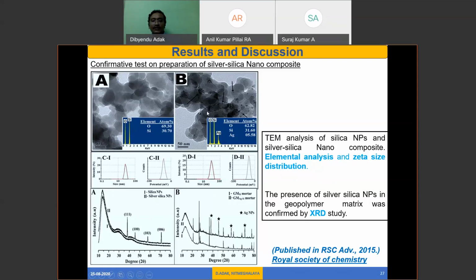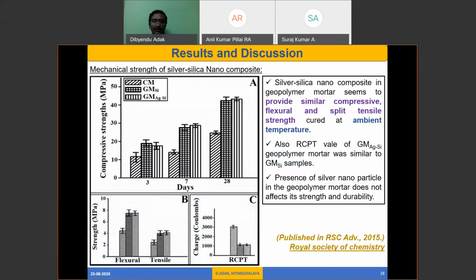Based on the 6% silver silica nanocomposite and silica nanocomposite, these are the compressive strength studies. What we can see is that after 28 days of curing at normal environment temperature, the geopolymer concrete with silver silica and normal nano silica gives almost the same strength, near about 41 or 42 MPa. Similarly, flexural strength is almost the same, split tensile strength is almost similar, and the RCPT value is also the same.